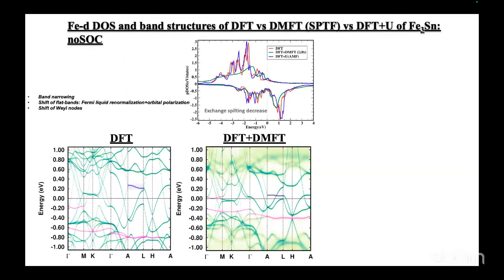These are the results that I got when I go from DFT to DMFT. This is the overall change that we see in the density of states and the band structure. We clearly see the effect of the correlation in terms of finite lifetime, that leads to band narrowing near the Fermi level. Also due to the orbital polarization, we see a shift of the near flat bands towards the Fermi surface, from minus 0.6 to nearly 0.6, and a slight non-dispersive band also comes near the Fermi level for DFT plus DMFT.